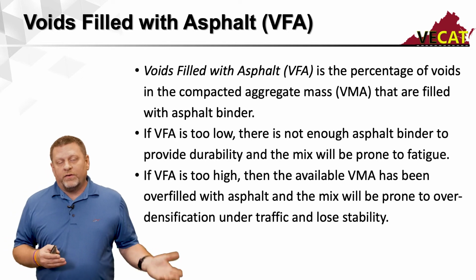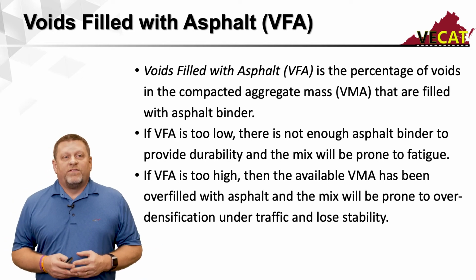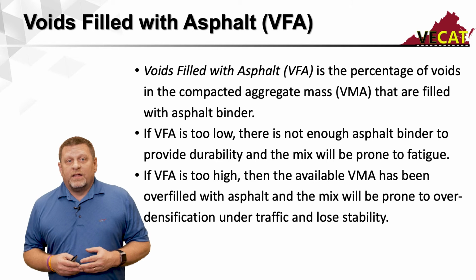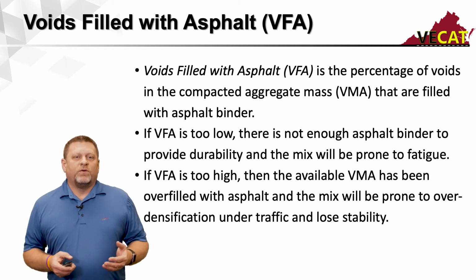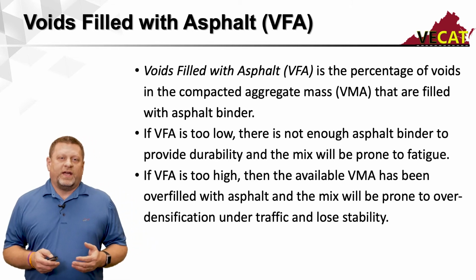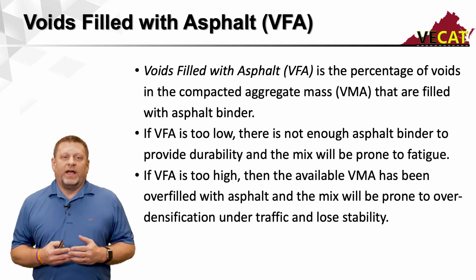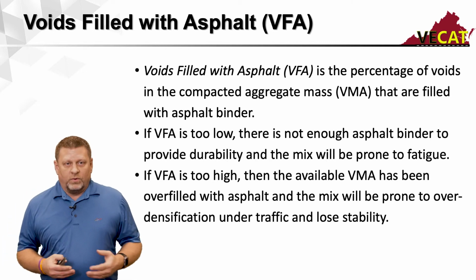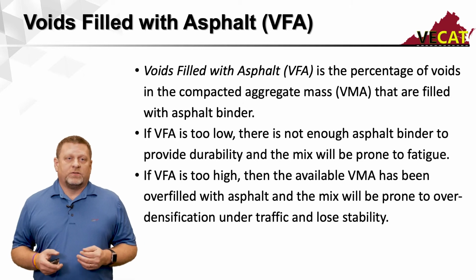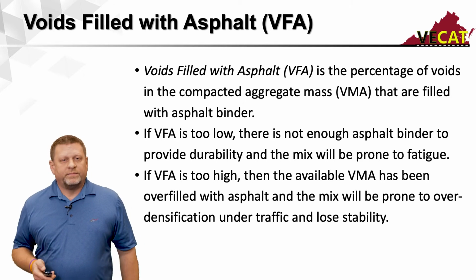But on the other end of this, the flip side, if the VFA is too high, then the available VMA has been overfilled with the asphalt binder, and the mix is prone to over-densification and possible rutting or other things can happen based on too much of the VFA.